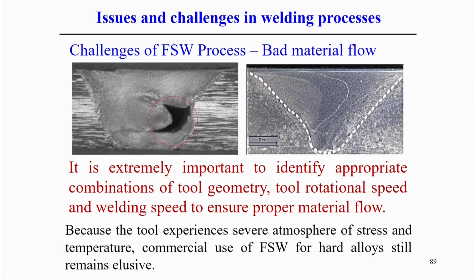Therefore, it is extremely important to identify the appropriate composition of the tool, the appropriate combination of the tool geometry and the other welding parameters, tool rotational speed and also welding speed, that ensure proper material flow. Then we can use this combination of parameters and expect a good weld joint.